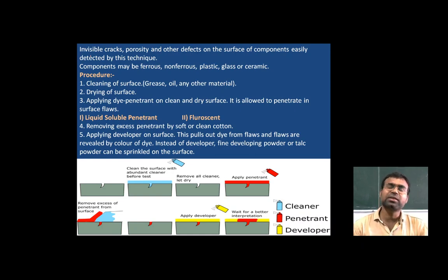Obviously, first we remove the grease, oil and other material available on the surface which is to be tested. How is it cleaned? Either by wiping with cloths, or by applying water, or applying some kind of chemical for cleaning. Remember this point: we will not utilize any kind of peening method to remove the scales and dirt available on the surface.